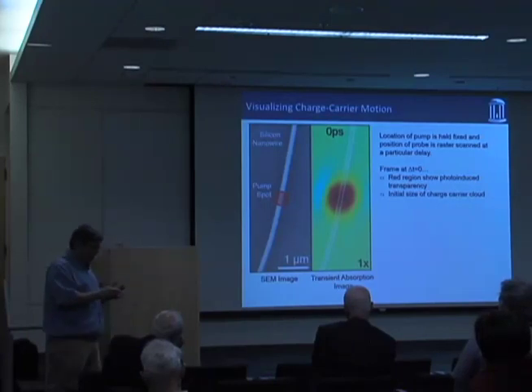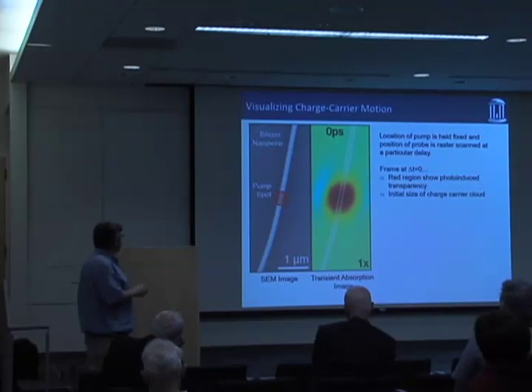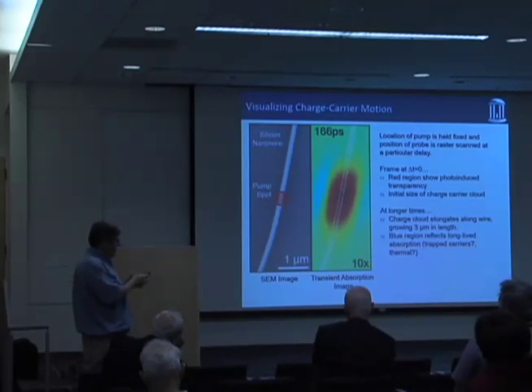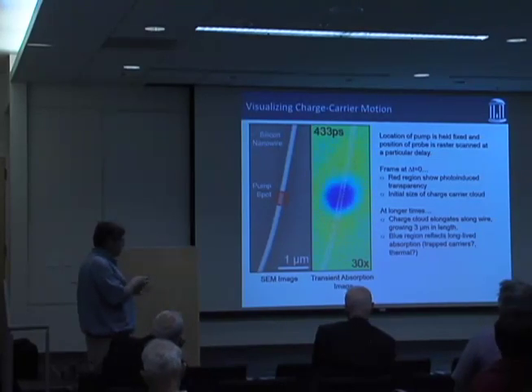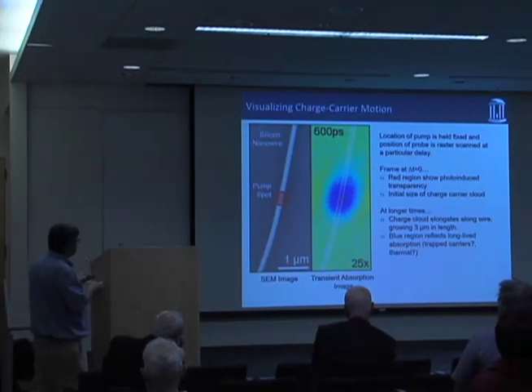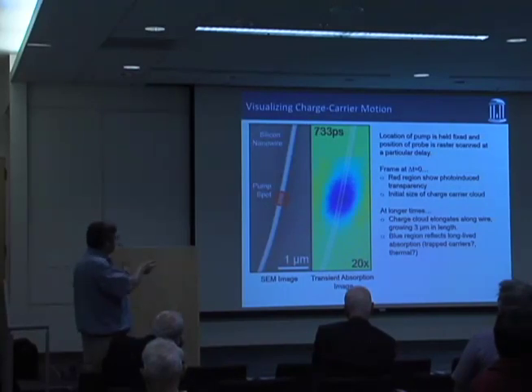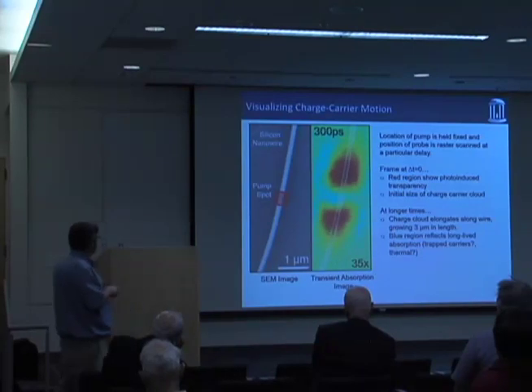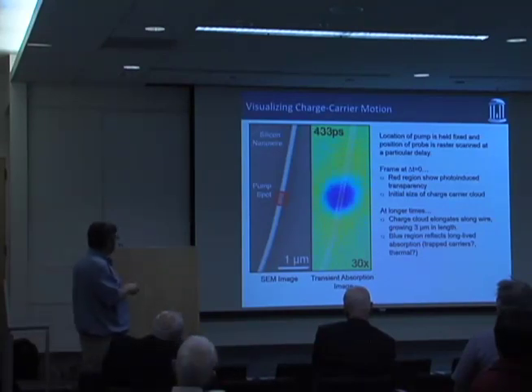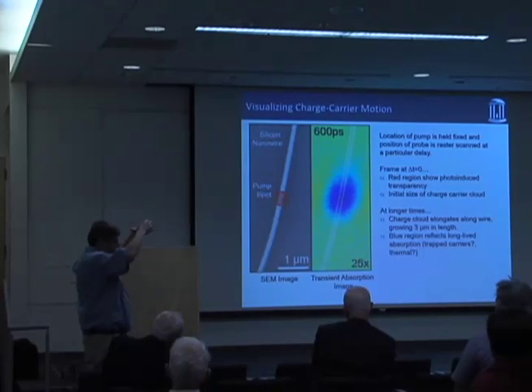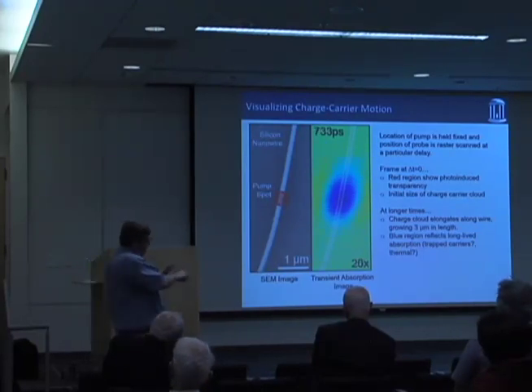Then if I take my time delay and collect images like this at longer delays, what you see is that as the delay gets longer and longer, and carriers move away from the excitation spot, the transparency also moves with it. So what you're looking at is the evolution of that photo-induced transparency spatially, which is also telling you about where the carriers go. It's going to cycle through again. It grows along the nanowire, and it's decaying in intensity, which is what this scaling factor tells you. So the whole image is coming down in intensity and spreading out.